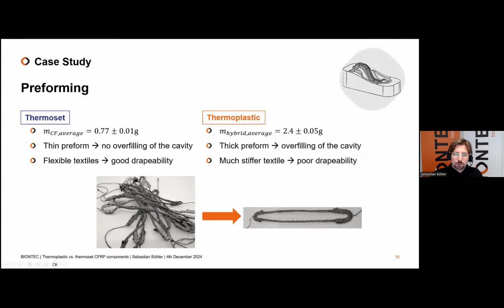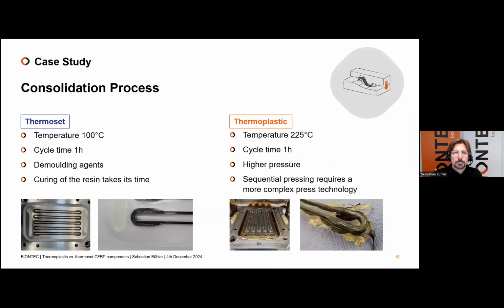Below you see the picture. Here you see the preforms. They are stitched; the white yarn is the stitching yarn, and you see the substrate in this case was washed away. After a drying process, you have a warping of the preforms, and before we put them in the mold, we stretch the preforms a little bit, and then we can put them directly in the mold, but we will see this on the next page.